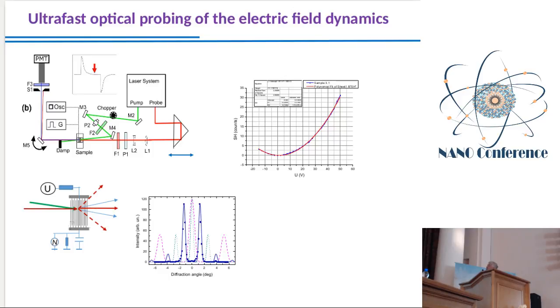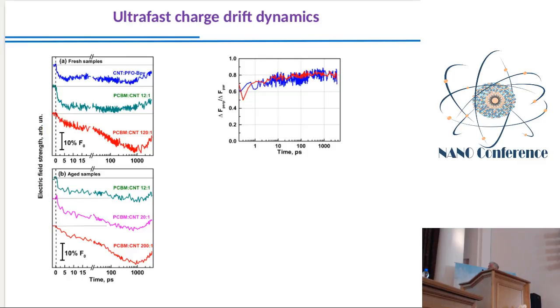Here are some results obtained by using this technique. The curves seem to be not very complicated, but in fact we can see several processes from this curve. Let's say this is when we have only carbon nanotubes wrapped with this conjugated polymer. In this case, charge carrier generation efficiency is low, but still when we excite with a femtosecond pulse, we see a drop of the electric field.